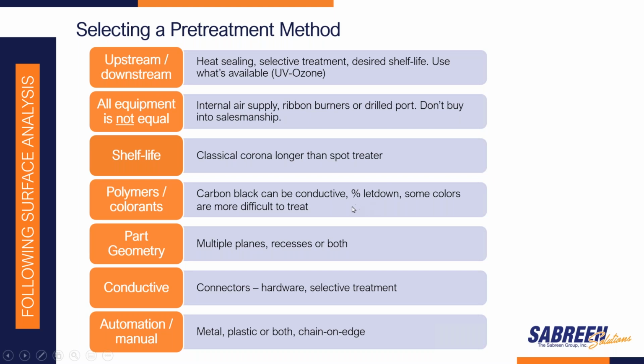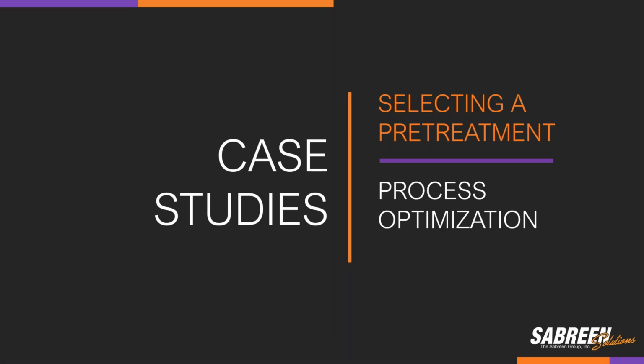The type of polymers and colorants. Remember that carbon black can be conductive and that there are critical threshold levels. The part geometry will affect which pretreatment method, and in some cases, in addition to the part geometry, components may have metal hardware. So that would make a difference on classical corona discharge, but it would not make a difference on atmospheric. Also, we want to look into our mechanical automation, how well we're actually automating.